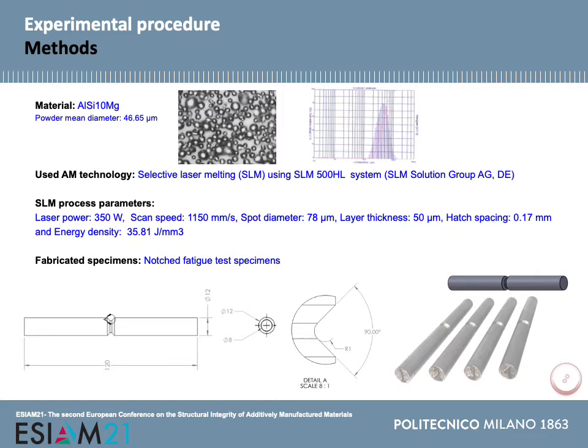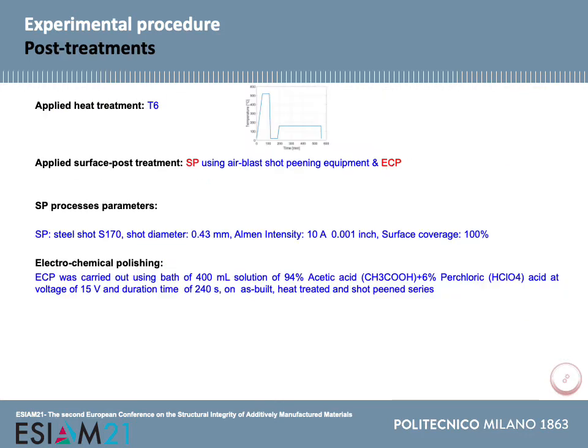In fabrication of the specimens, the value of 1 millimeter was considered to ensure that we can reach the notch root by applying shot peening to this area, also in both upward and downward skins. As post-treatments, half of the samples were heat treated using T6 thermal treatment, which is very common in aluminum alloys, and then shot peening and electrochemical polishing were used as surface post-treatments.